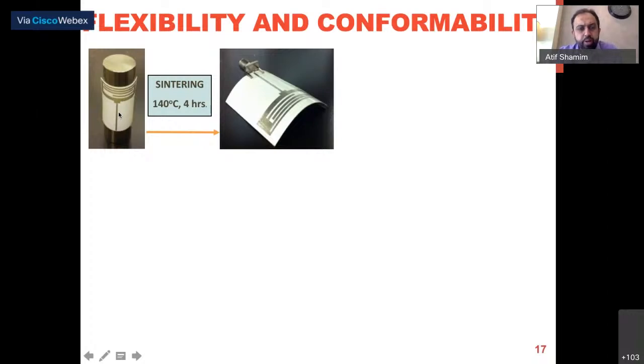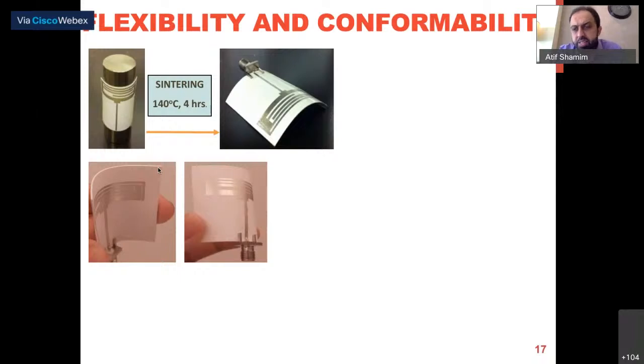However, there are other types of papers where the polymer coating is not there, so they remain flexible after heating as well. So you could bend them whichever way you want. They work very well in flexing as well. And the beauty of printing is that you could print on a number of substrates. As you could see here on the top right, we printed a dual band antenna on a leather substrate, right? And we also printed a multi-band antenna on a Kapton plastic substrate, which is also flexible. We even printed on a textile, on a normal t-shirt, right? Which I will talk about a little bit more later on. So this is the stuff which you probably cannot do with conventional PCB technology.